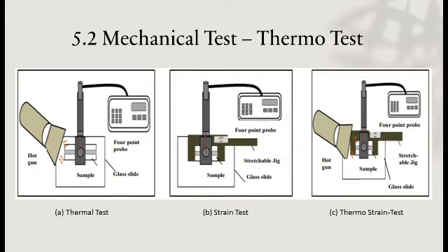And then for figure B, the strain test, the sample was stretched at different levels at room temperature. The sample is stretched under strain levels of 0%, then 20%, 40%, 60%, and 80%. The initial length of the sample is 20 mm, and the samples were stretched until they reached the maximum length, which is 36 millimeters. Then the samples were left to stabilize for 30 seconds before the resistance was measured at each strain level. That is for the strain test.